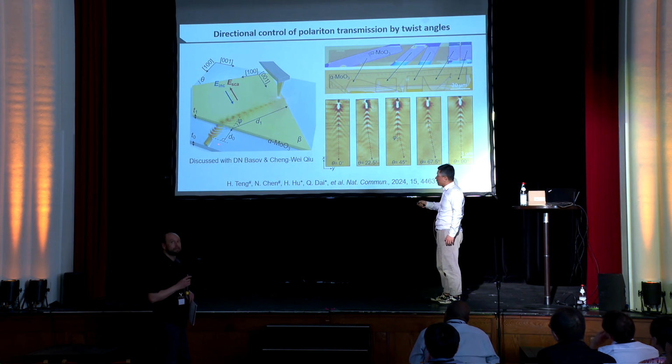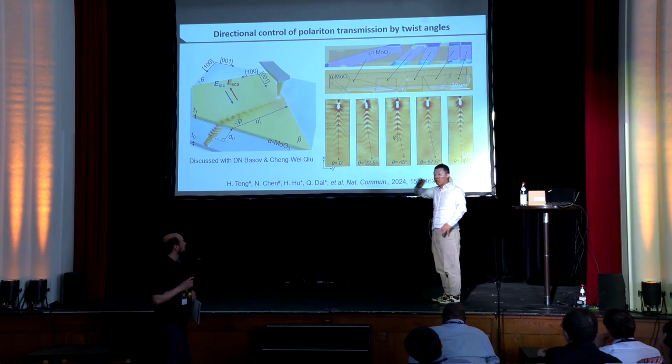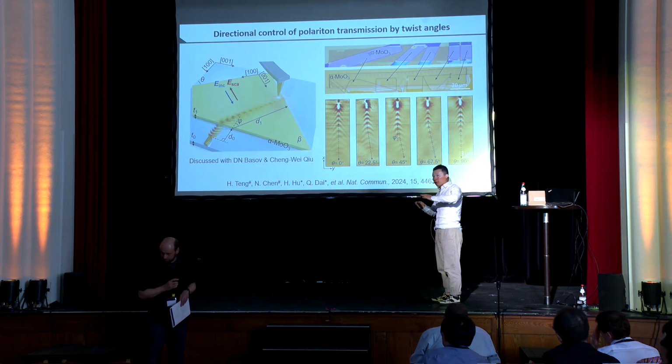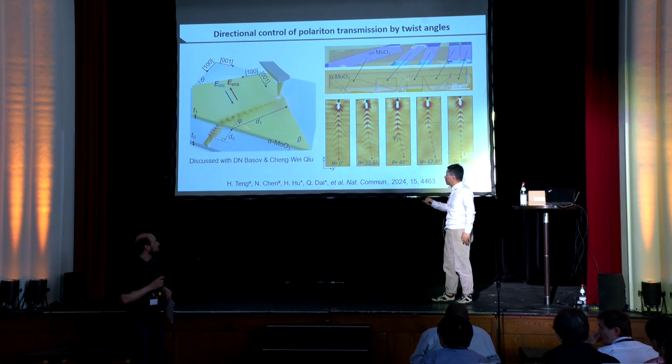Also, the antenna can scatter this illumination, and combining this resonant plasmon and the scattered light, you can cover a lot of wave vectors, right? These wave vectors can cover the dispersion of this polariton. So because of momentum conservation, you can excite this kind of polaritons. Hope that helps a little bit. Thanks.